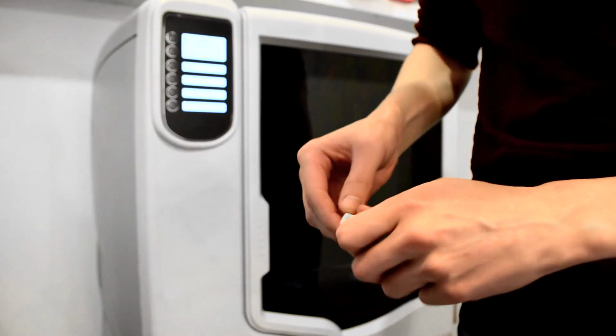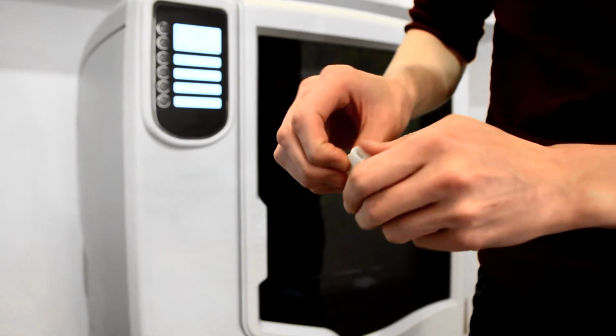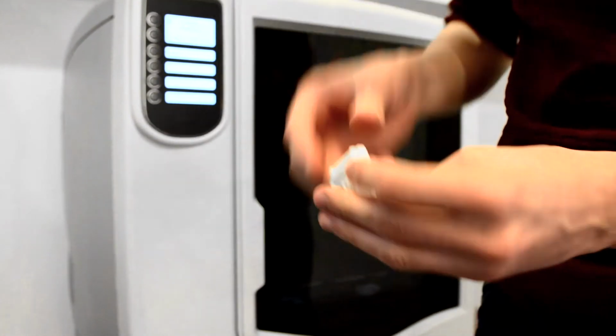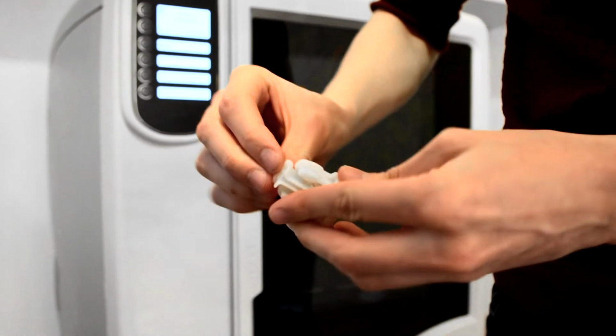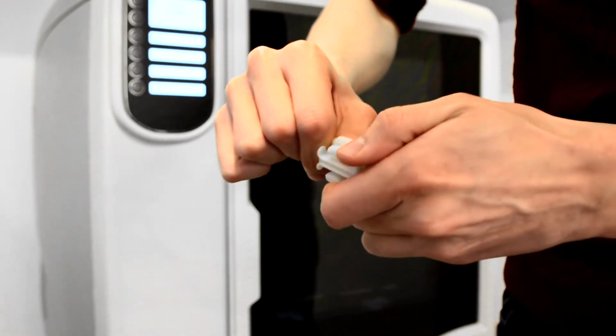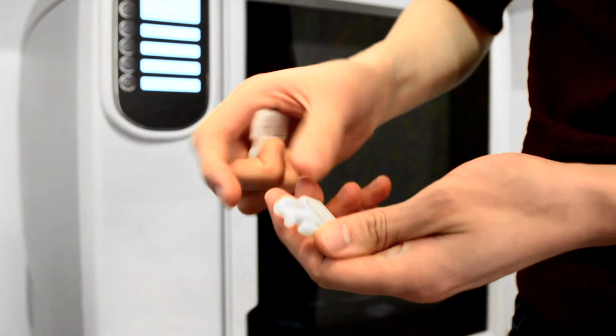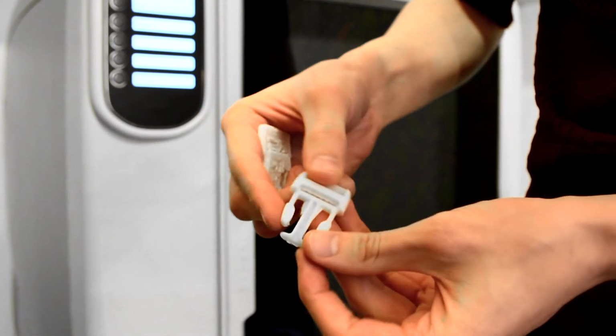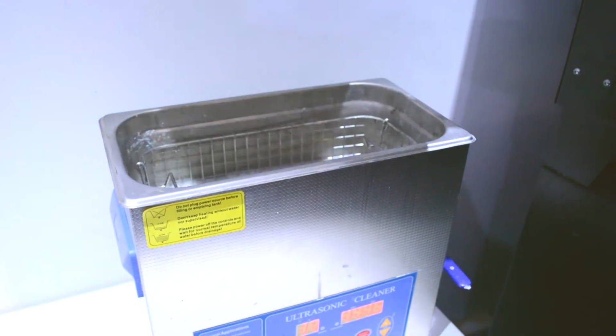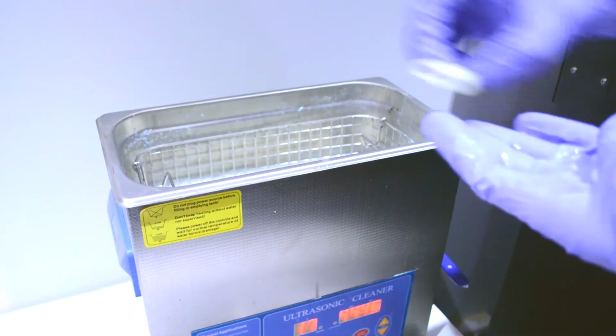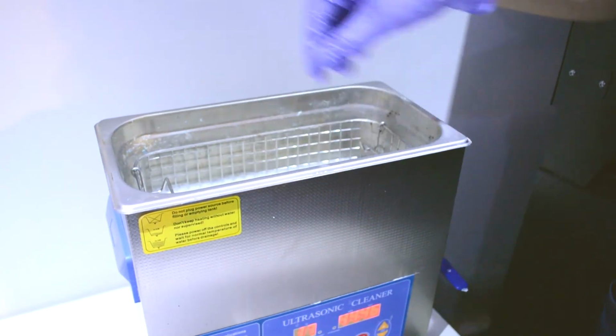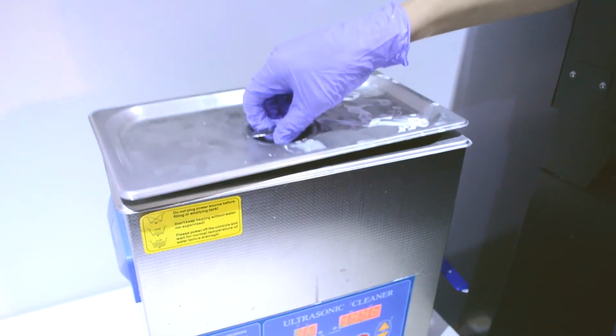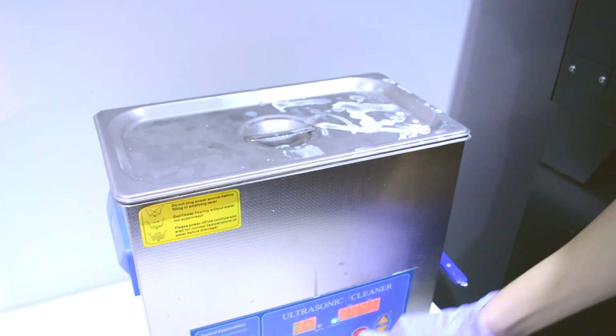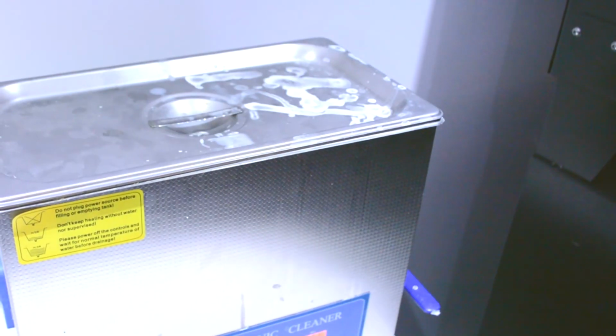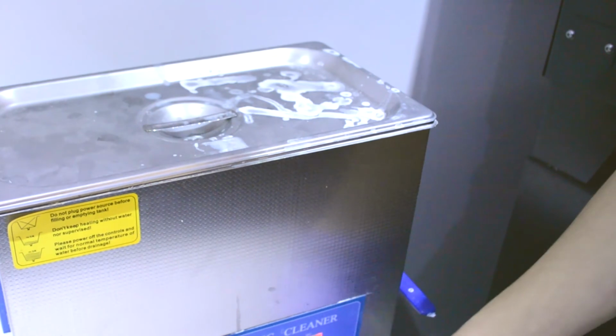Depending on the geometry, it is sometimes not necessary to post-process the models, and the support material can be simply broken away by hand. In other cases where the models are very complex, delicate, or have areas which cannot be accessed to remove support material by hand, it is simply dissolved in a hot caustic solution. Dissolving the support material uses a caustic bath at 80 degrees Celsius for around 4 hours. The heat of the bath softens the support material, and the effect of the caustic solution and some agitation wash away the support material, leaving behind the finished model.